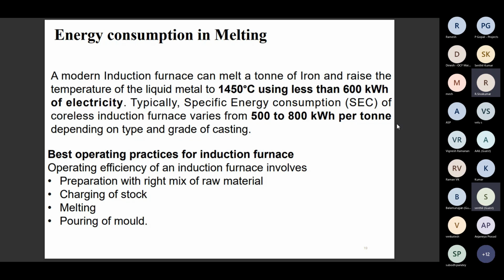So there is a possibility of saving in the melting alone, a minimum of 50 to 60 units, by using best practices, the best technology, and the best operating practices. For induction furnaces, operating efficiency involves preparation with the right mix of raw material, charging of the stock, melting, and pouring of mold. These are some of the practices we can see one by one.